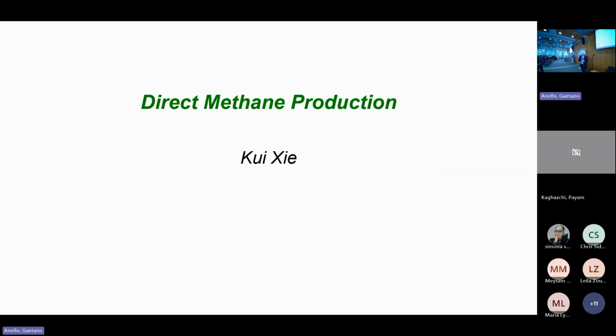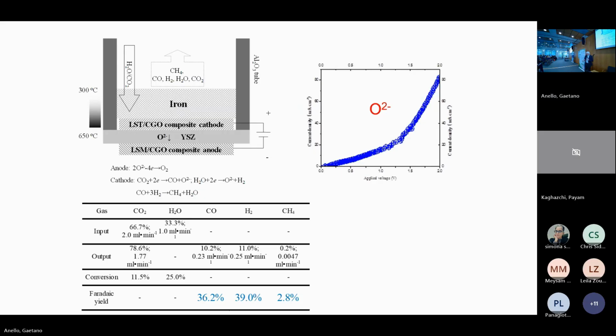Looking at some of the first work, we had a visiting PhD student from China, Kui, who is now a professor, and you'll see more of his results later on, but he looked at direct methane production. First of all, with an oxide ion conductor, he used an iron and oxide layer to bridge from 650 to 300, because the products we produce in solid oxide electrolysis will often decompose. Through that, he was able to get CO2 conversion and steam conversion, and it produced about 2.8% methane, mostly carbon monoxide and hydrogen. But you can produce methane in a solid oxide electrolyte and electrolysis.